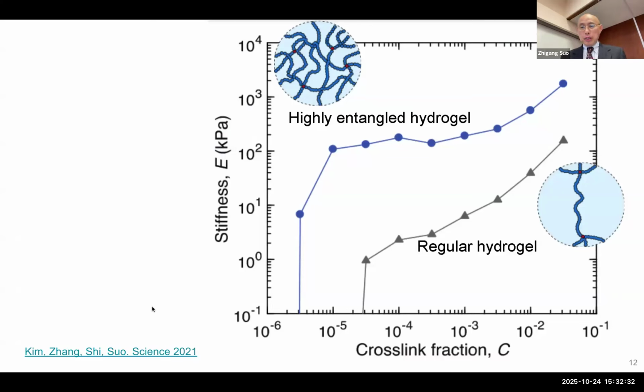So for regular hydrogel, you can see this is logarithmic. Modulus is orders of magnitude lower, regardless of however many crosslinks you put in. This is the issue. Now for Tanglemer, the highly entangled hydrogel prepared this way, both hydrogels are stable in water.